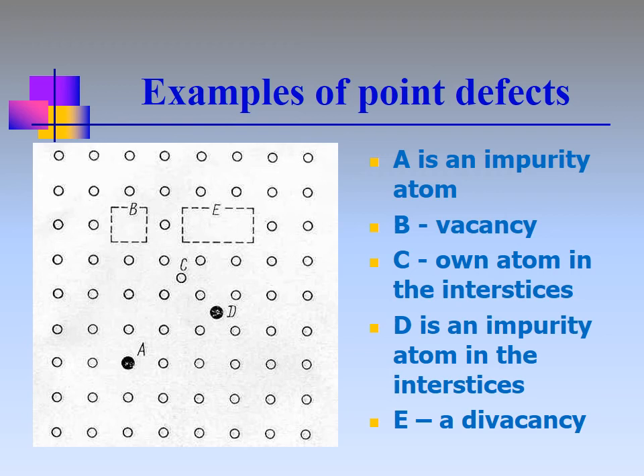determined by the concentration of impurity point defects and their valence structure. Excess valence electrons contribute to N-type conductivity and excess holes contribute to P-type conductivity. Therefore, in semiconductor crystals, impurity atoms have a particularly strong effect on the electrical conductivity. For example, introduction of one boron atom into 100,000 silicon atoms increases the electrical conductivity of silicon by a factor of 1000.